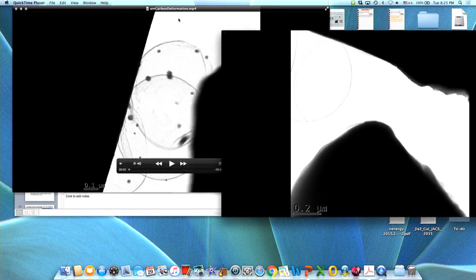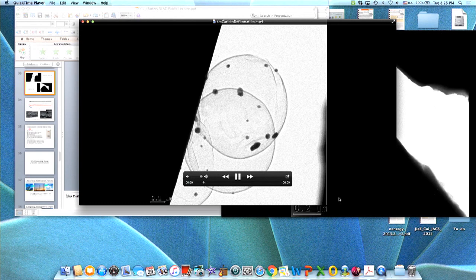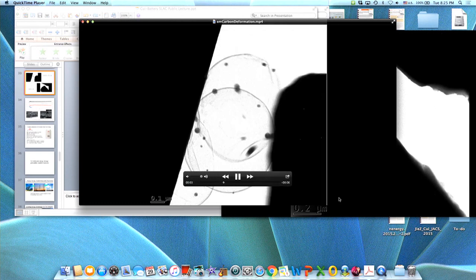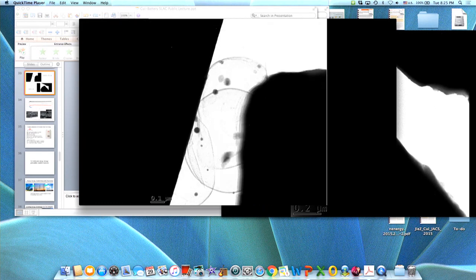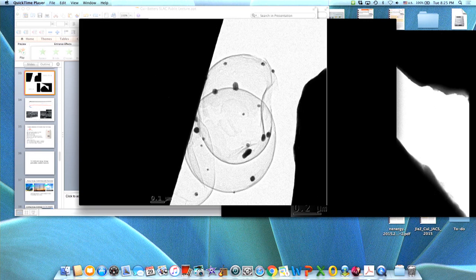This made us think this is a great material to function as a cage. If silicon breaks inside, it's kind of like silicon bounces onto the graphene and pushes the graphene, graphene doesn't break, and then it gets contained inside. But if you look at amorphous carbon, that's right here. Push on this amorphous carbon, now you take it back. You see, it doesn't bounce back anymore, it's broken.